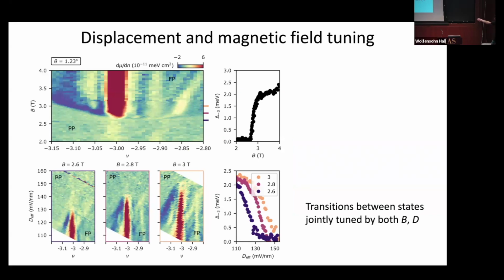At nu equals 3, in fact, this is a metal insulator transition, so we can look at nu equals -3 as a function of magnetic field, and there's some point at which it goes from metallic, basically, to quite insulating. Interestingly enough, this is not just a magnetic transition. So it's tuned by magnetic field, but if we change the effective displacement field for a given fixed magnetic field, you can also drive this metal insulator transition as a function of displacement field. So there's some difference in layer polarization at nu equals 3, or layer polarizability. And so we're still sorting out what the ground state may be. But the takeaway is that both electric and magnetic fields can be used to tune many of these transitions that we observe.